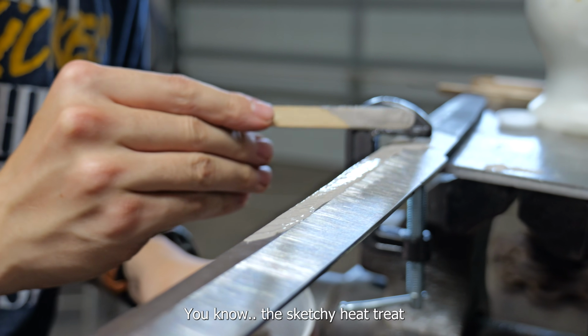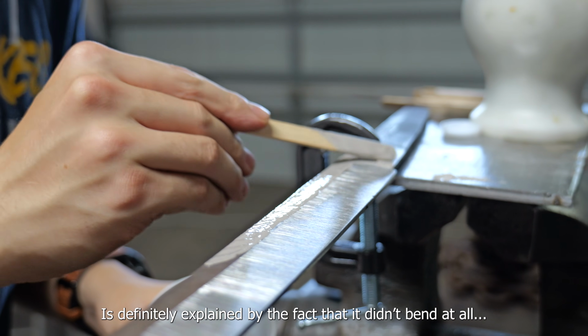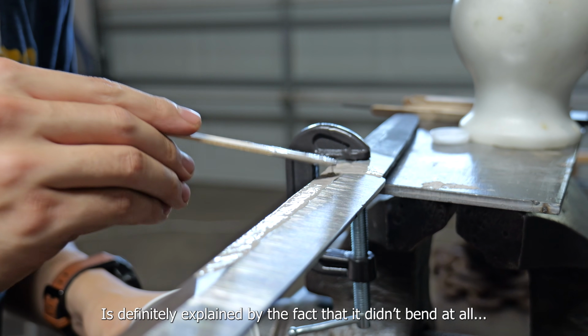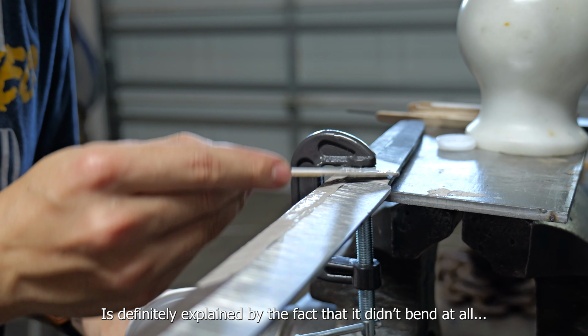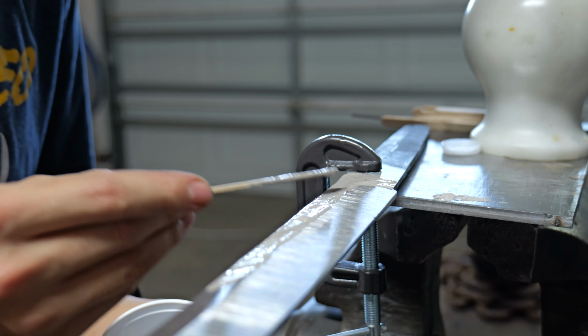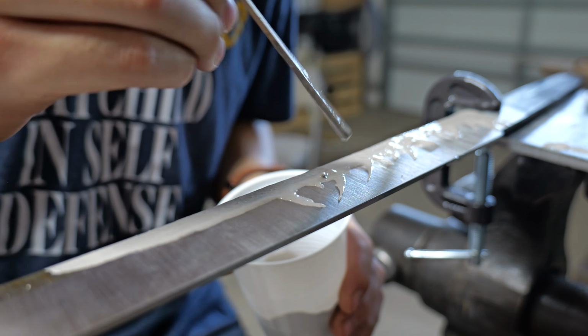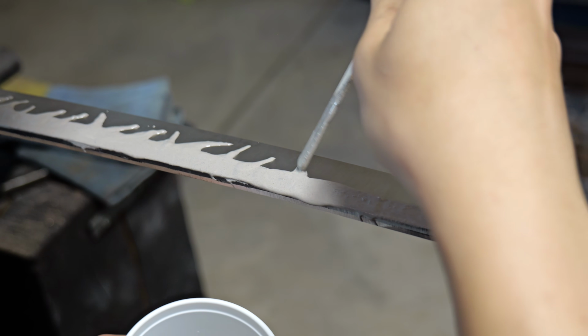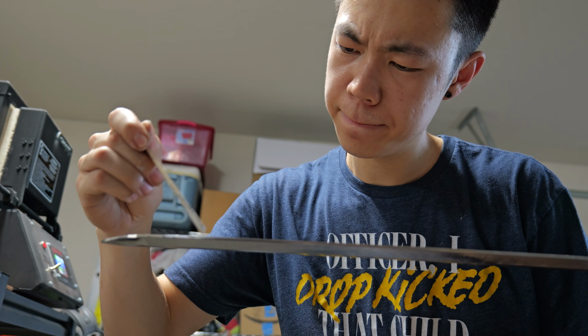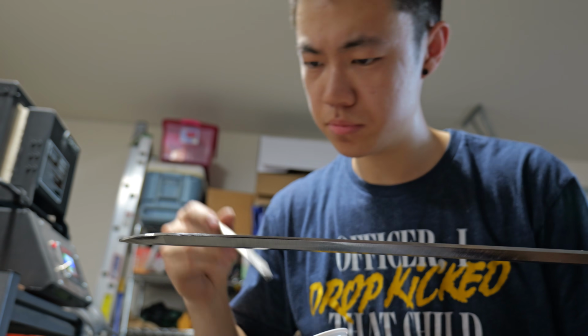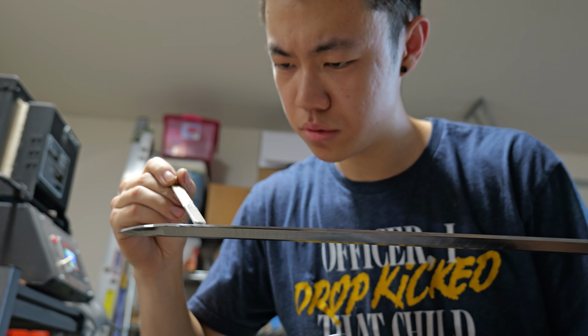The sketchy heat treat is definitely explained by the fact that it didn't bend at all. You can see here, my clay is much more aggressive, and I didn't actually put any ashi lines. I was hoping that this would make the hamon pop a little bit better and help with the heat distribution.